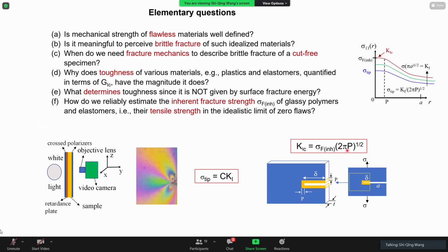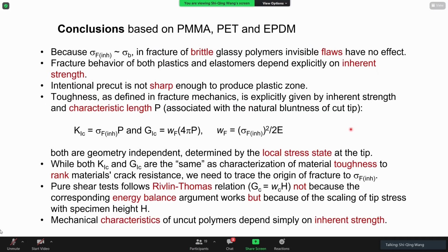It has to do with how blunt the cut is, or how the material responds during fracture, in terms of a natural length scale coming into the problem. So with that, I reach the conclusion. Basically, we set out to find that the inherent strength and nominal strength are similar. Therefore, this problem of fracture in our glassy polymers is not really a problem of invisible flaws making it weaker. It's not weaker, it's just what it is.